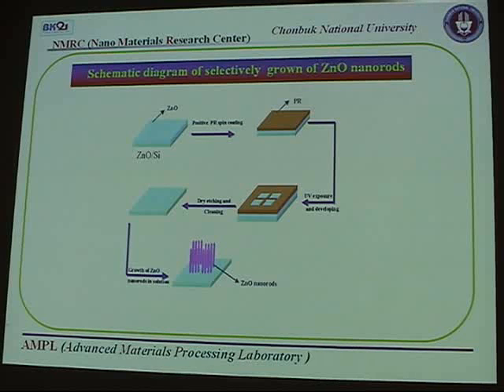Here, this diagram presents the schematic view of selectively grown zinc oxide nanorods. First, we coat the silicon substrate with a zinc oxide layer, and then apply PR spin coating, where we use positive PR. Finally, we use ICP, inductively coupled plasma, also called dry etching, to pattern the substrate for growth of zinc oxide nanorods at selective positions.